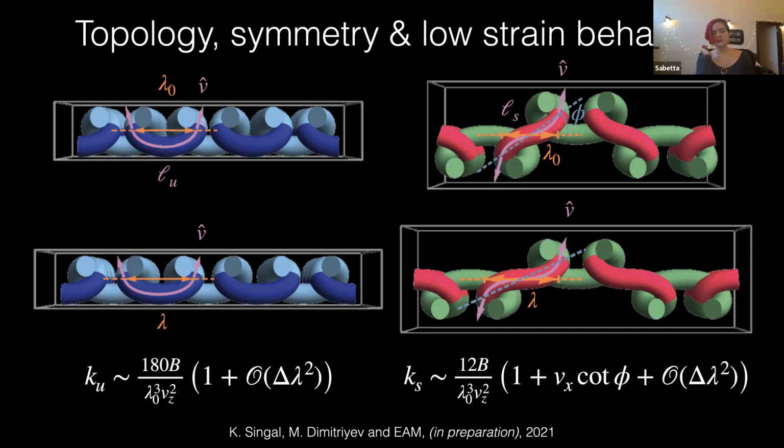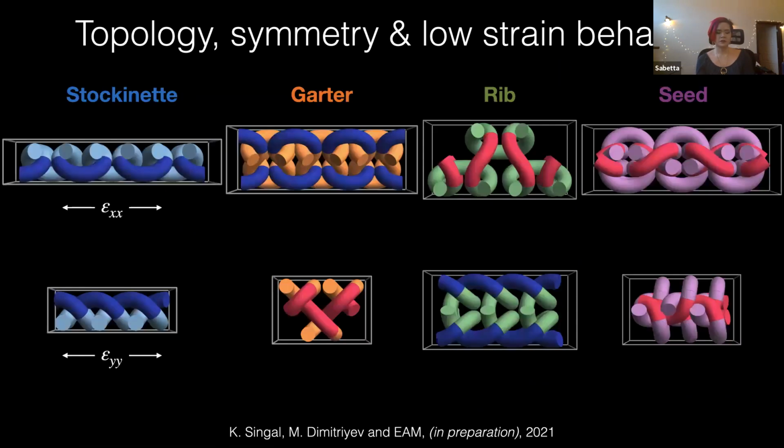So then there's one extra term that's of interest, which is this term here, which is saying that the initial starting angle, what this phi is, matters. So if I'm vertical, it costs me no additional energy pretty much to have a rotation. But if I'm horizontal, it's basically infinite energy because I can't extend the yarn.